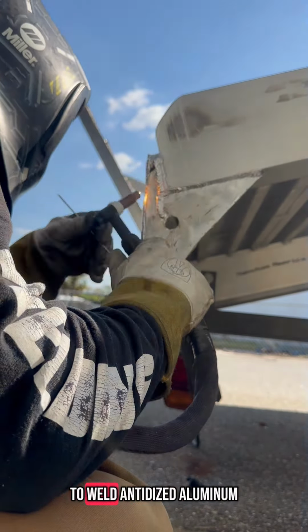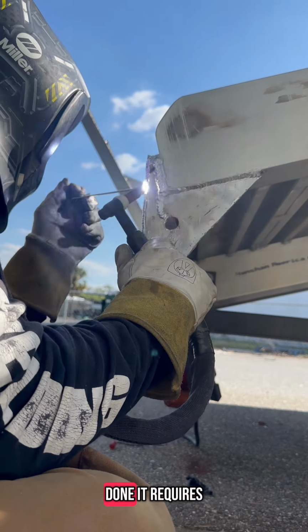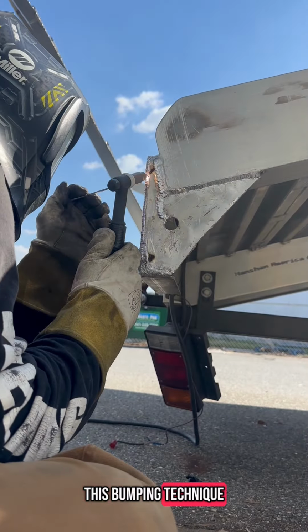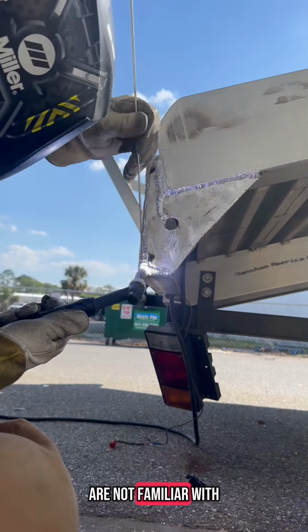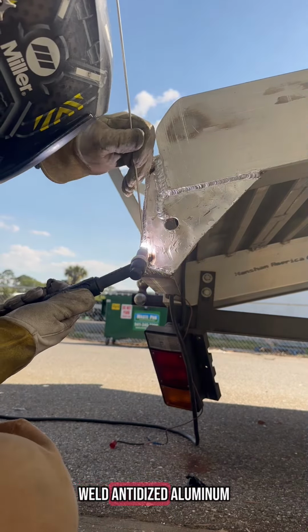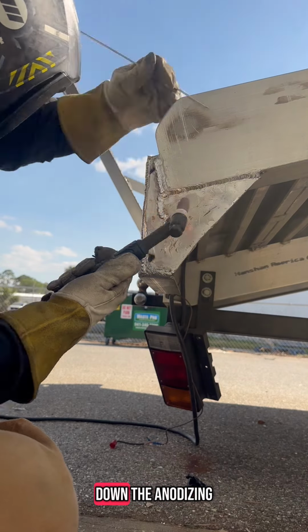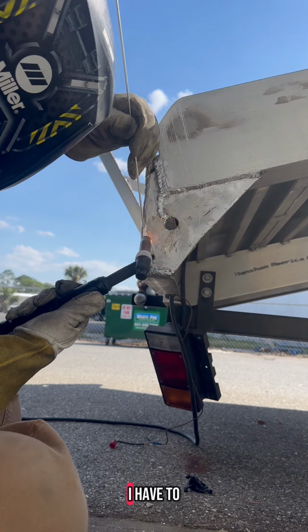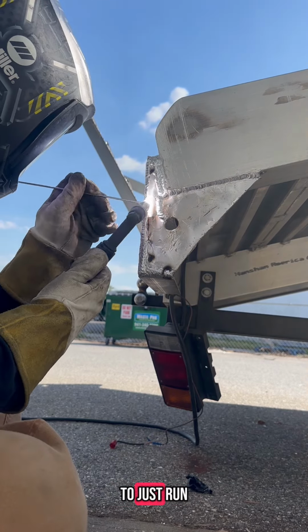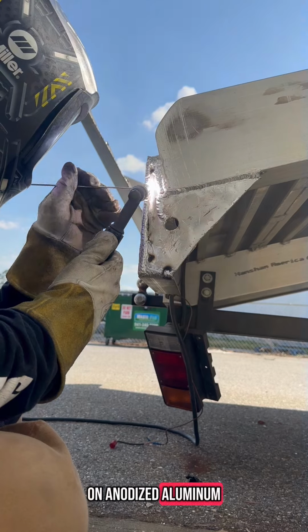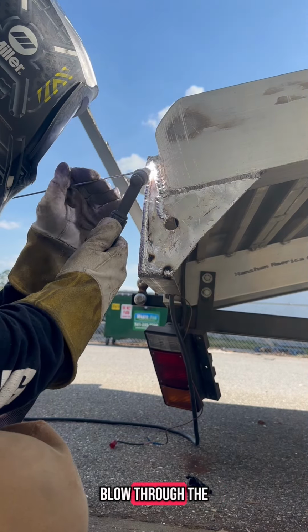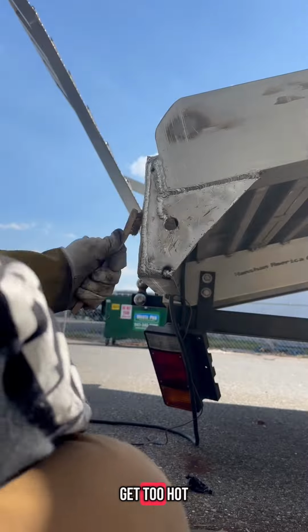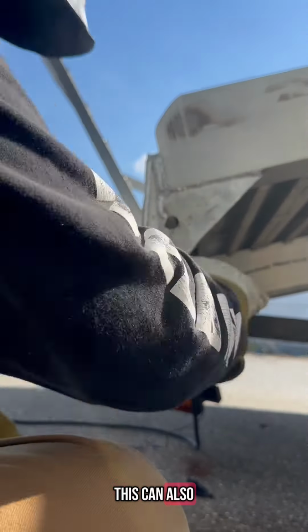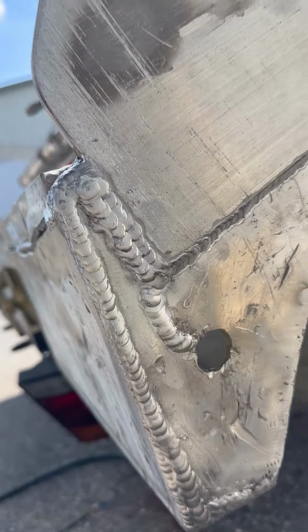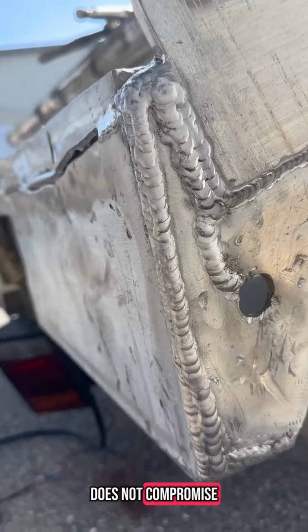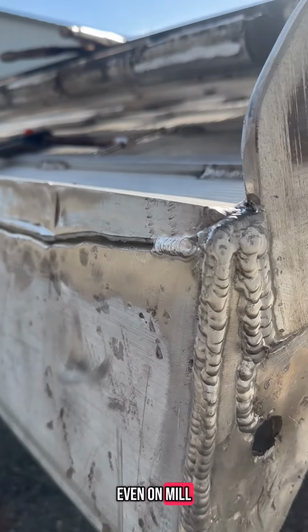But in order to weld anodized aluminum, which can be done, it requires this bumping technique, which most people are not familiar with. Before we can weld anodized aluminum, I have to break down the anodizing, and in order to do that, I have to start and stop. If I were to just run a straight weld on anodized aluminum, I would actually blow through the entire part because it would get too hot too quickly. This can also be used on mill finish aluminum. The bumping technique does not compromise the integrity of the welds, even on mill finished aluminum.